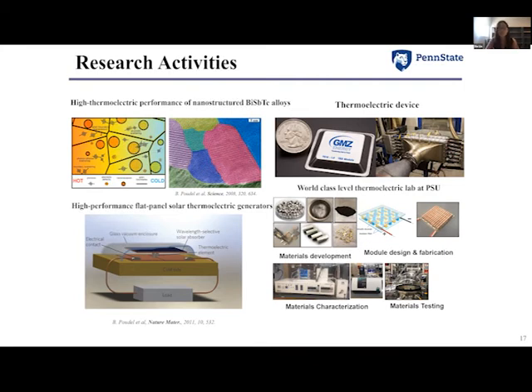The nanostructured engineering for thermoelectric technology was proposed to significantly reduce the thermal conductivity of these thermoelectric materials so that this ZT performance can be enhanced. Back around the year 2000, the ZT in bismuth telluride-based bulk alloys had remained around only one for more than 50 years. During Dr. Bed Poudel's PhD at Boston College, he successfully realized the nanocrystalline bismuth antimony telluride bulk alloys.